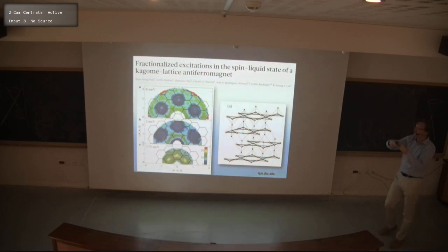And it turns out that if you calculate the structure factor for that kind of excitation, recognizing that you have bonds in this lattice which are oriented in 3 different ways, then you actually will generate this particular pattern in momentum space. So somehow it looks as if I'm just breaking individual singlet bonds on the lattice.